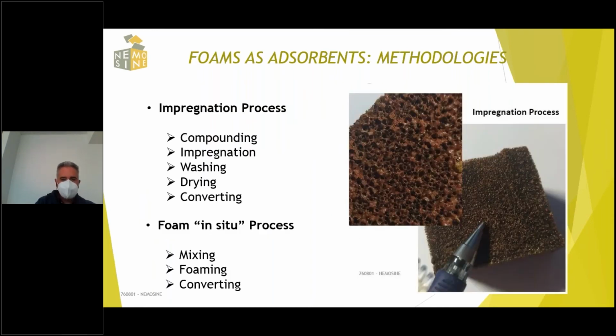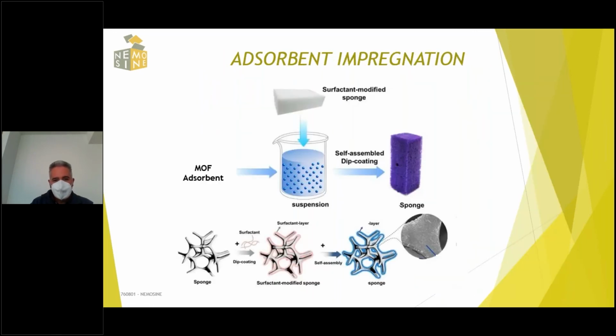Well, the first system of foams impregnated with MOF material that we tried to prepare was the impregnation process. The impregnation process is a complete process that implies compounding, impregnation, washing, drying and converting, while the foam in situ process has a mixing, a foaming and converting process. Basically, this is the diagram that represents all the steps related to the adsorbent impregnation.